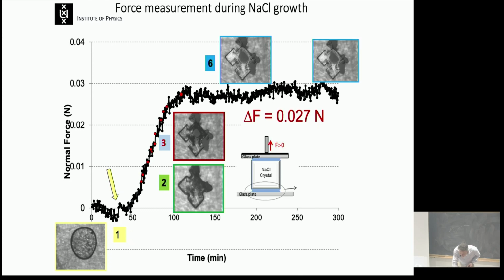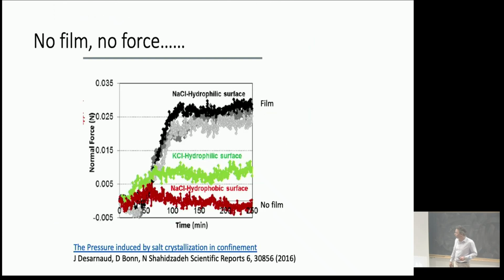What is perhaps more convincing is that you can do a treatment where you make the surfaces hydrophobic. They're glass surfaces, so I can do a simple silanization treatment. If I have a sodium chloride crystal on a hydrophilic surface where water can easily form a film, I get this large force. But the red curve is a sodium chloride with a hydrophobic surface. We don't see a film and we don't measure a force. This is really cool, because it's really evidence that this layer should be there.